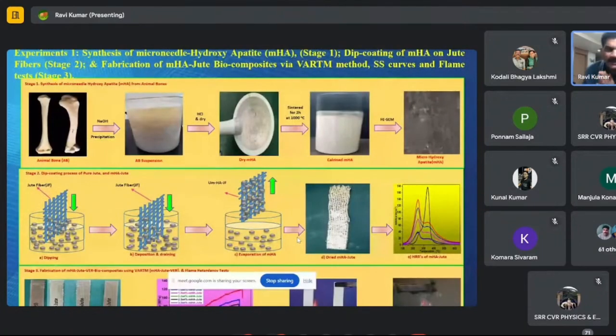So how we made the experiment is important for the learning students. Here, stage 1 is the synthesis of microhydroxyapatite, stage 2 is dip coating of MHA on jute fibers, and stage 3 shows fabrication of MHA jute biocomposite via the VARTM method, and stress strain curves we also studied through this slide. Here you can see the bone, and we decomposed it with strong NaOH, like 28% NaOH we took. And after 20 days, it was converted into a suspension.